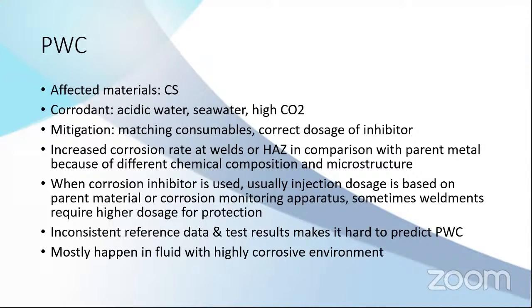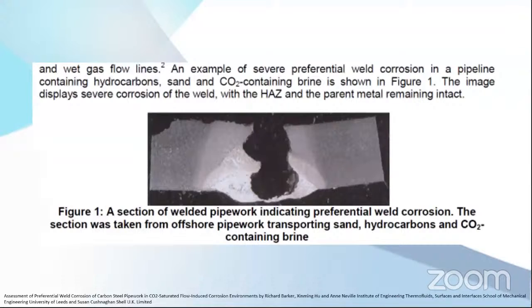And this PWC happens mostly in very corrosive environments. If it's mildly corrosive, it normally doesn't happen, so you get the same corrosion resistance between the parent material and the weldments. But in a very corrosive environment, it can be different. The weldments probably get attacked faster than the parent material. So this is just an example of weldment PWC in a CO2-containing brine. So you have chlorides there, you have CO2 there,